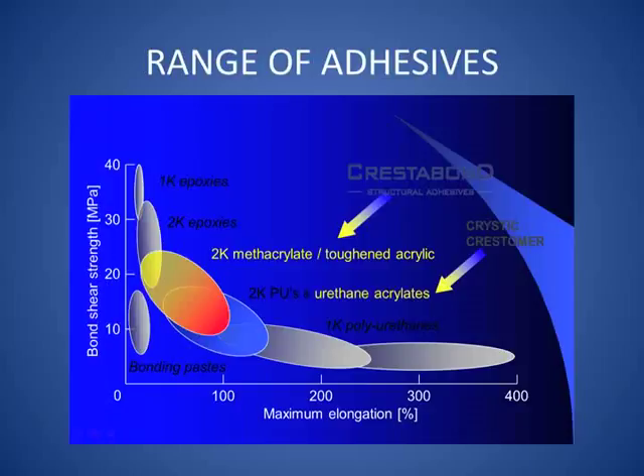So a little background information. Adhesives come in a bunch of different forms. This is a fairly simplistic look at a range of adhesives from epoxies through methacrylates and on to basically simple polyurethanes. On the vertical axis, we've got their lap shear strength. When you're doing a test, you put two parts together and you lap them and you pull them apart. And that's the best way to load adhesives. We'll see that later. The other axis is elongation. You can get a lot of stretch out of some adhesives, but sometimes too much stretch, not enough stiffness, is a bad thing. So you've got to look at the application and balance the strength with the toughness.